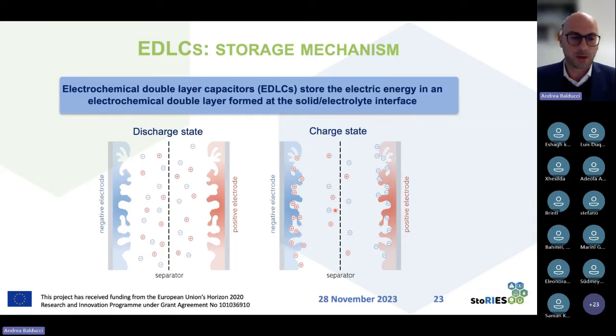Why? Because we have two carbon electrodes that can be polarized, and in the discharge state, when none of them is polarized, the ions of the electrolyte are, of course, dispersed in the solvent. When we are charging, in the electrode, which we see here is negatively charged, for example, the positive ions of the electrolyte get closer to this electrode and form this double layer.